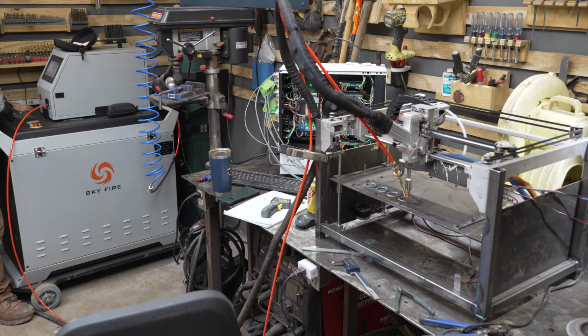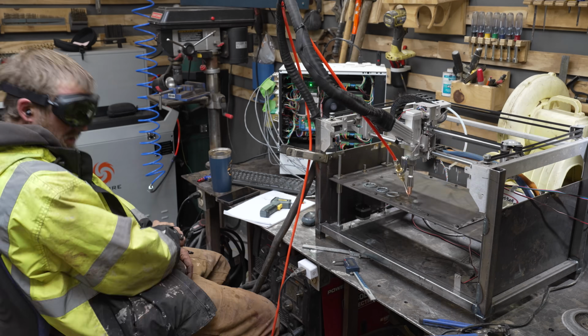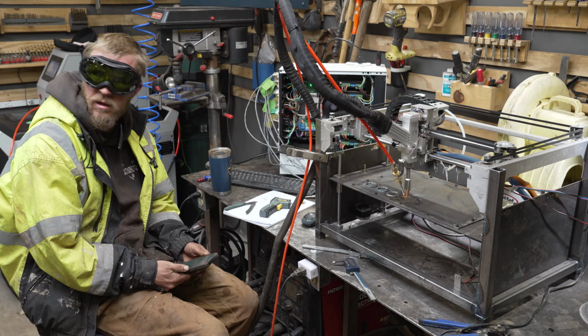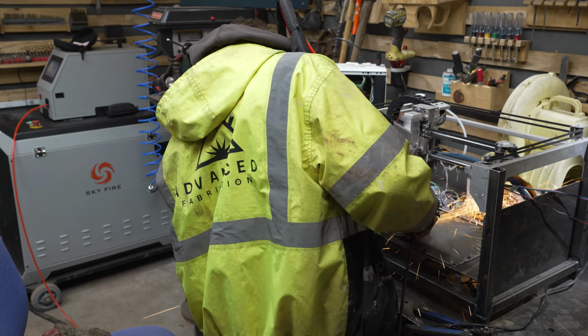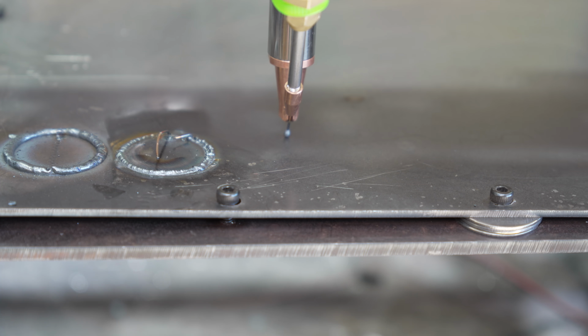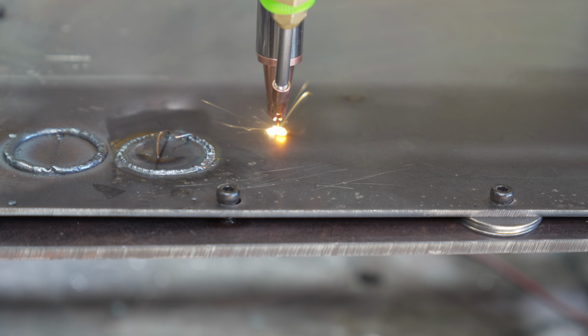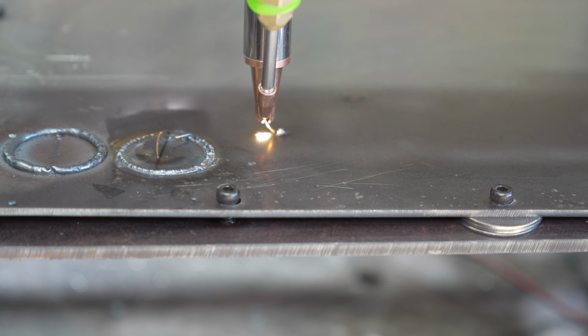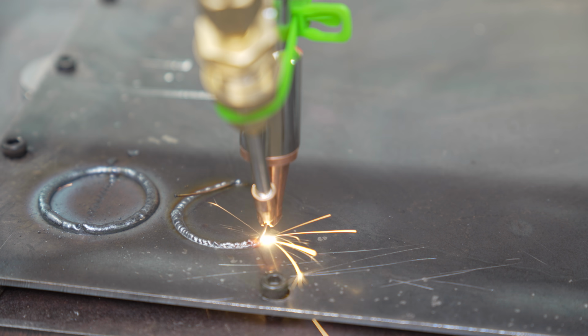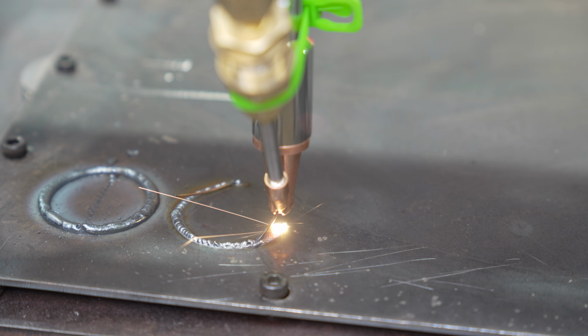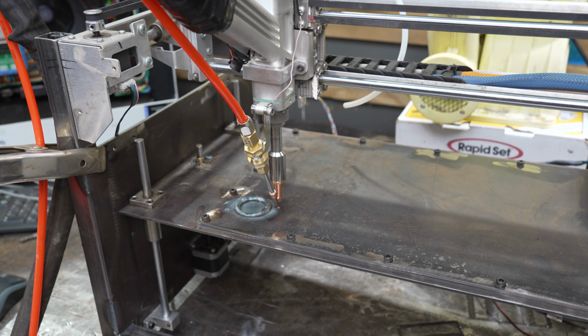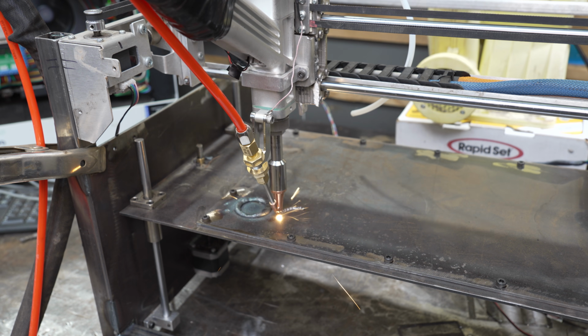As you may be able to tell from this time lapse, I had trouble actually printing layers again. I found that the height of the print head was absolutely crucial to be in the correct position. Too high, and it would drop little droplets of metal onto the part and get stuck. Too low, it would miss the puddle entirely and get stuck. Well, shit, we haven't had that problem in a while. I eventually figured this out, and we got our data.